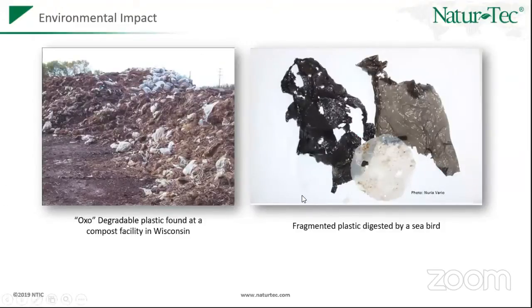So here are some pictures of what happens when some of these bags end up in a composting facility. You can see that oxo-degradable bags don't compost and they create a lot of litter within the composting facility. And they also break down into such small fragments that these broken down fragments are now very difficult to collect. So let's imagine you have a PET bottle on the road. Now, if it stays as a PET bottle, it's easier to collect. But if this PET bottle becomes small fragments, then it becomes very difficult to collect and recycle. So from one product, which is potentially recyclable, by using oxo-degradable technologies, it gets converted into a product which now cannot be recycled and which creates a completely different set of challenges to manage.